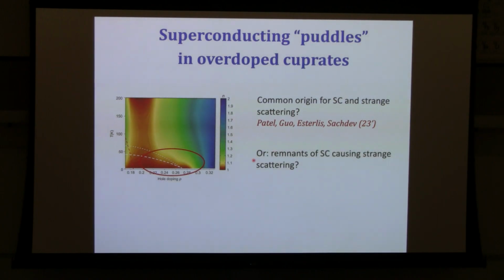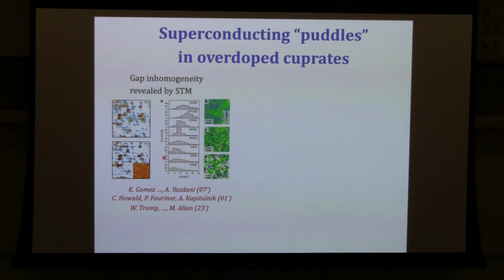We actually pursued a different approach. What if it's the remnants of superconductivity that exist even when global superconducting phase coherence has been suppressed, either by applying a high magnetic field or by raising temperature? Once again, the system is microscopically inhomogeneous. So we suppress global superconductivity. The system globally is a metal, but there are local remnants of superconductivity that remain throughout this entire regime. What if it's these remnants that are causing the scattering, which is giving rise to this linear in T resistivity? So what are these remnants?